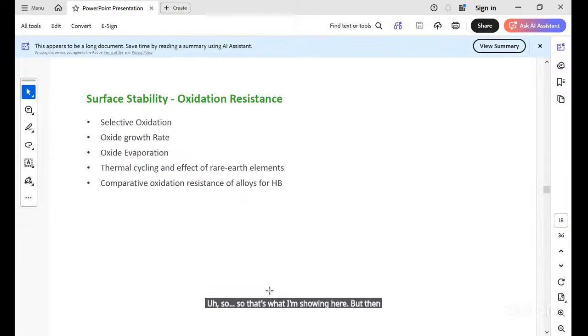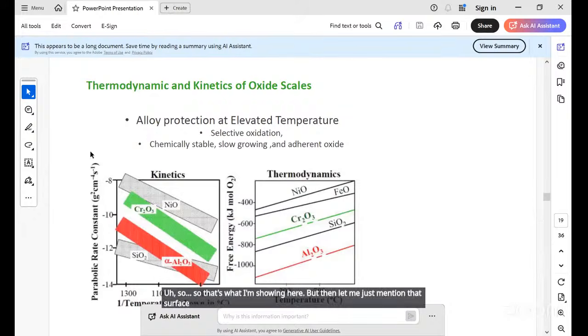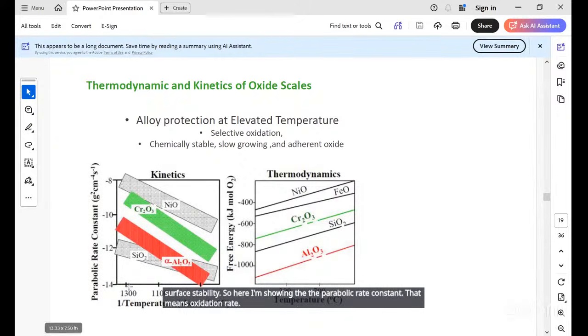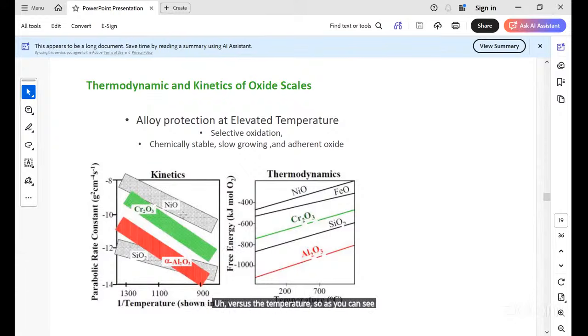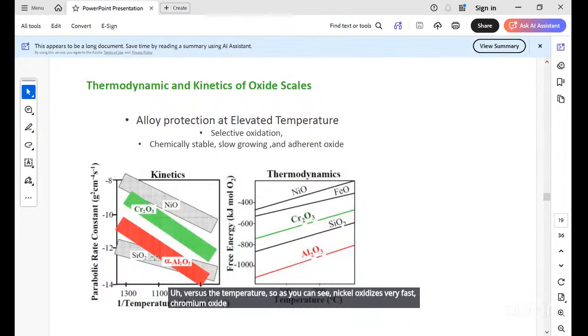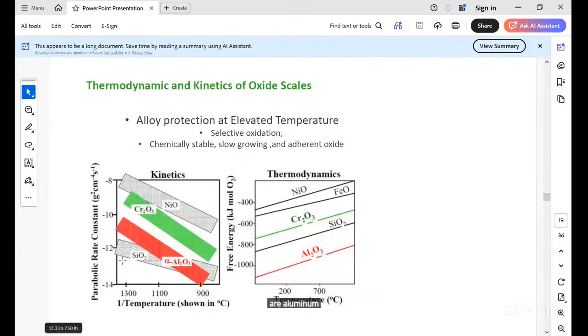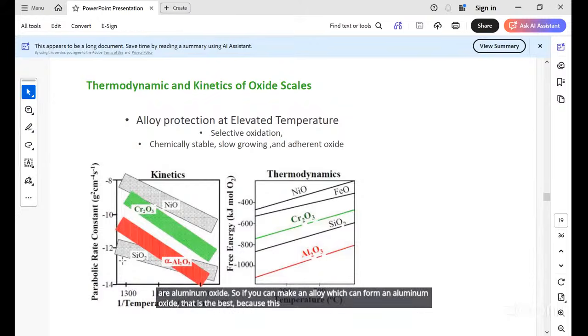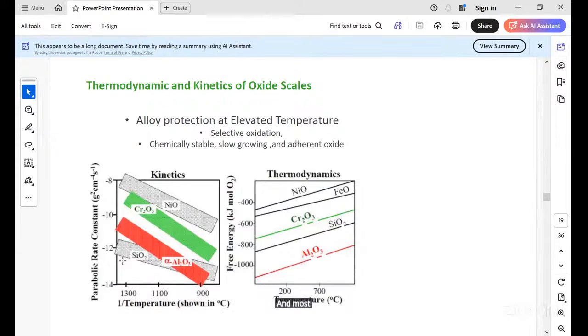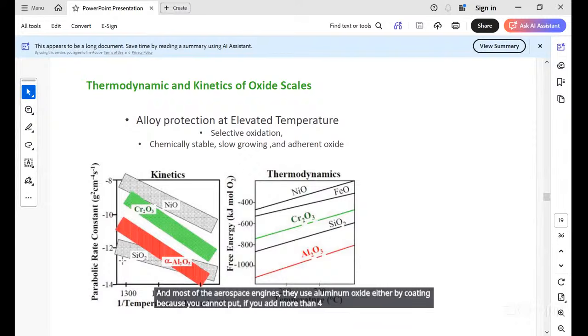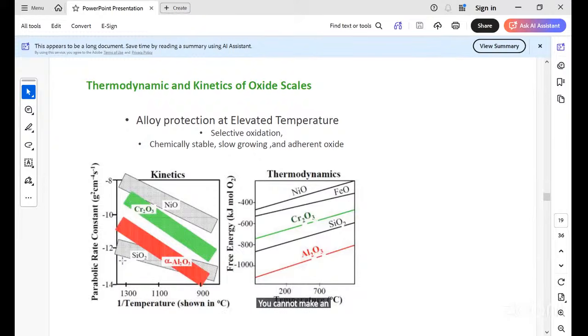But then let me just mention the surface stability. So here I'm showing the parabolic rate constant. That means oxidation rate versus the temperature. So as you can see, nickel oxidizes very fast. Chromium oxide next, and the best are aluminum oxide. So if you can make an alloy which can form an aluminum oxide, that is the best because this oxide will grow very slowly. And most of the aerospace engines use aluminum oxide, either by coating, because if you add more than 4% aluminum in the alloy, its high temperature properties or even room temperature properties are very bad. You cannot make a workable alloy.